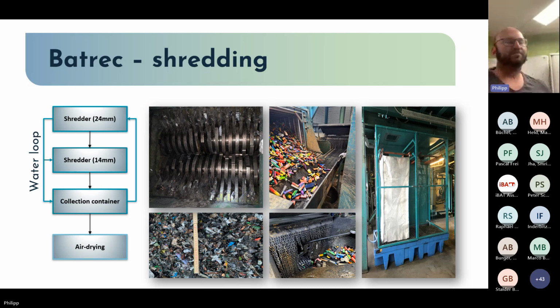you need three parts for a fire. So oxygen, this is available because of the active material. You need something burnable, so this could be the separator foils, and activation energy. And because of the storage in water, we can remove or reduce this activation energy, and so we are relatively safe that we don't have fires in our storage. Then, for example, here you see a lot of e-cigarettes. We turn the boxes, bring this to the conveyor belt and feed the shredder unit.